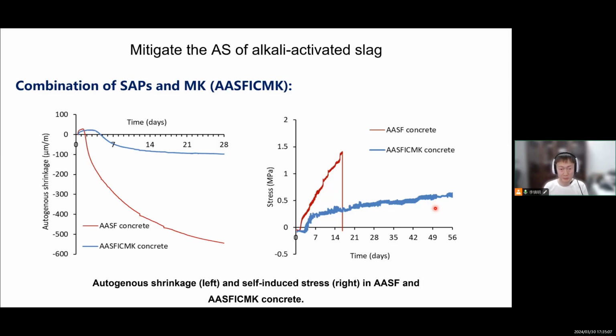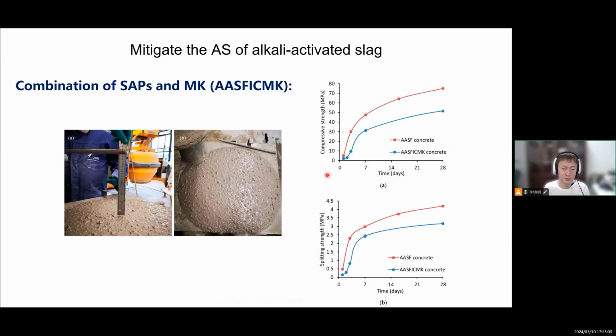So it's really helpful. And also the concrete strength is lower, of course, because you have SAP and metakaolin, which influence the reaction. But the strength is not that low. It's still more than 50 megapascal, which is already sufficient for a lot of applications. And also the splitting strength is not low, 3 megapascal. And also the workability is very good. So we think this kind of strategy is very promising to be used in concrete and structures.